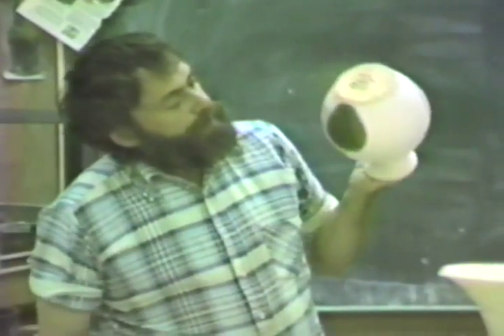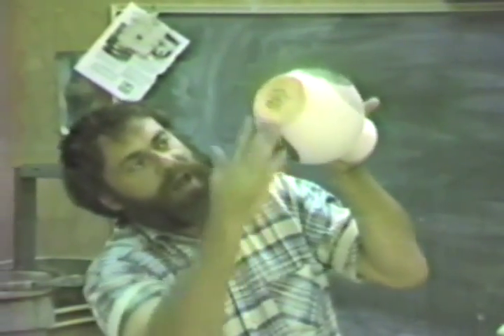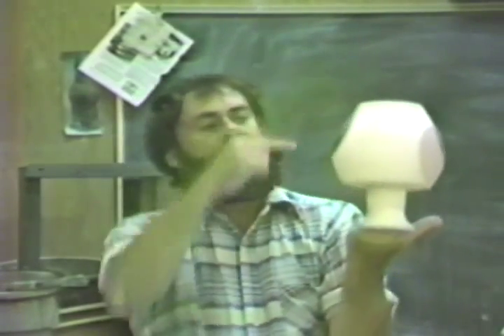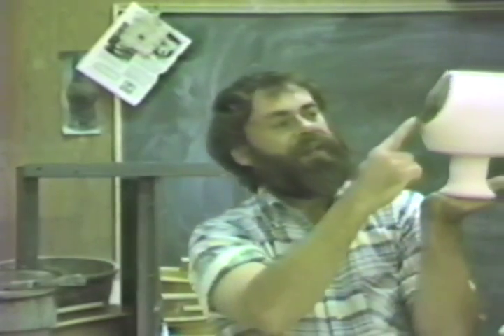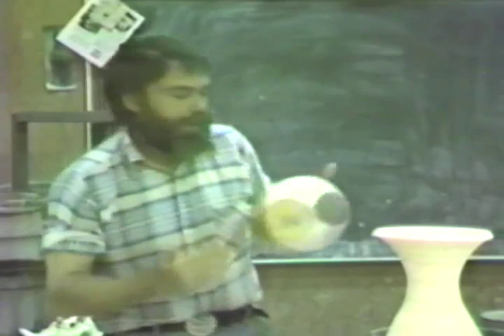You can see that. But one of the things that's important when you're dipping is, when you dip it down into the glaze, hold it this way for a certain amount of time until you can see that the glaze is actually drying. If you take it out and hold it like this real quick, or hold it like that, you could get a run that will run down the side of the pot, and it may not be what you're after. Okay, I'm just going to dip this quickly. I'm going to rub a little bit of this glaze off and then dip it quickly, see if I can get a hard edge on this one too. So we get a hard edge on both of them. And set that down.